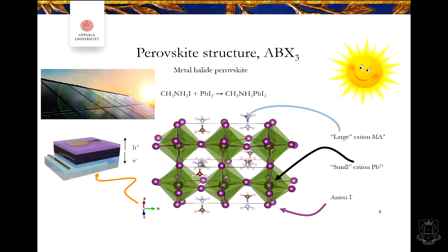Perovskite materials, these metal halide perovskites, are produced from solution, and they crystallize at low temperature. So it's low temperature processing, around 100 to 150 degrees. And here you see one of the simplest structures. Here we have methyl ammonium iodide and lead iodide, and that creates the perovskite structure, methyl ammonium lead iodide, with the formula ABX3.